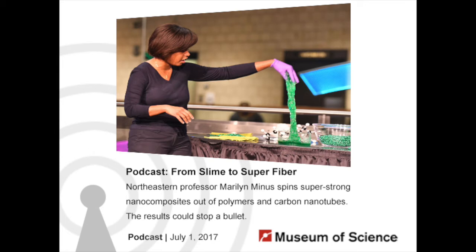Some of the polymer chains in the fibers of a textile are jumbled up, some are aligned. When you think of a jumbled up fiber and you move it, like when you move a knot, you're going to slide one fiber or one polymer across the other. Sliding doesn't take much energy. But once you pull that strand straight, in order to keep pulling it, you're eventually going to break it, and that actually takes more strength. So if we add in the weak stuff, which is the sliding, and the pulling, which is stronger, you usually get a fiber that has an intermediate property. So textiles for us have intermediate properties, but I can rip one, so that's still relatively weak for a human.